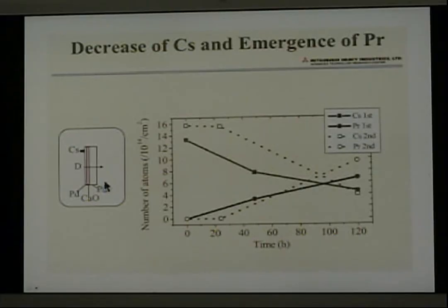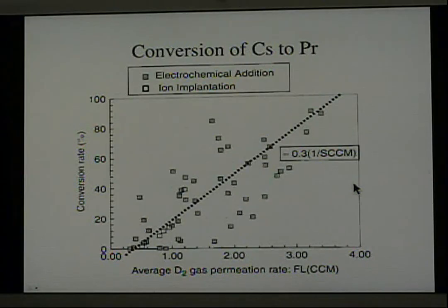Well, here's the result of the diffusion. They analyzed the surface using X-rays, and this is the concentration in 2 separate samples of cesium, and this is the concentration of the expected product, praseodymium. And you notice over time the praseodymium concentration increases and the cesium concentration decreases on the surface. They find that the conversion rate of cesium to praseodymium is proportional to the amount of gas that has passed through the sandwich. And there's a linear relationship between the two.